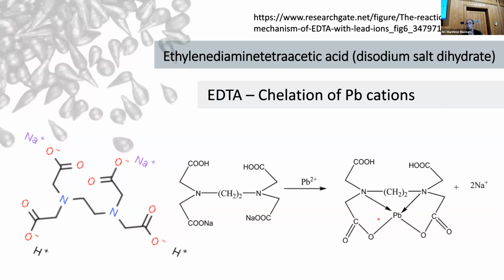But how EDTA works in a system is that you have our EDTA molecule over here. So here's our two sodium groups, and here are the hydrogens that, when they are put into water and dissolved, deprotonate. So they essentially dissociate from their molecule. They go into solution, which of course creates acidic conditions. So the solution for EDTA is generally a low pH, and it usually lowers the solution to between 4 and 6, which isn't too severe. It is still a pretty weak acid. And again, since this was designed for use in biological systems, that kind of makes sense, that we don't want it so acidic that it burns us from the inside out or something like that.